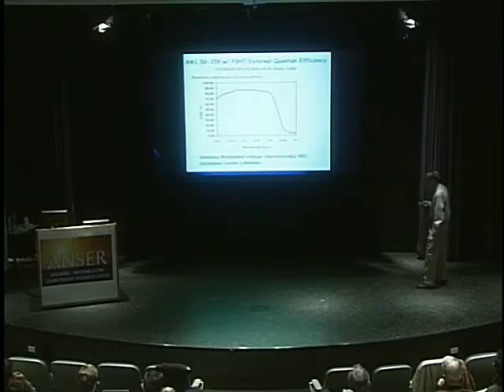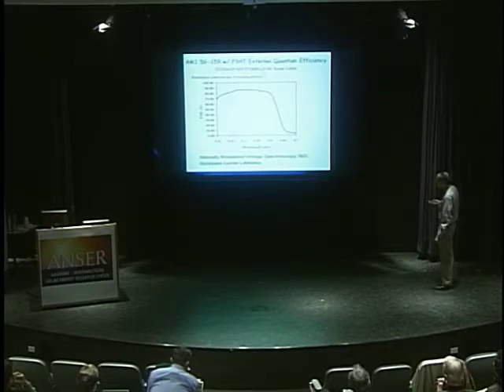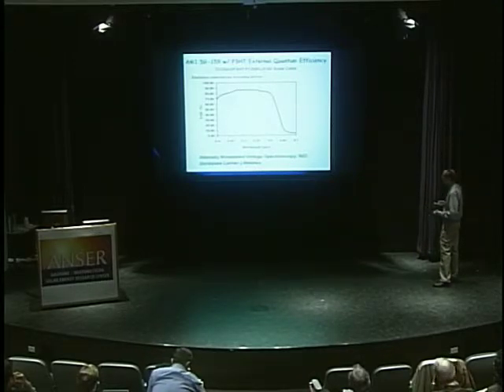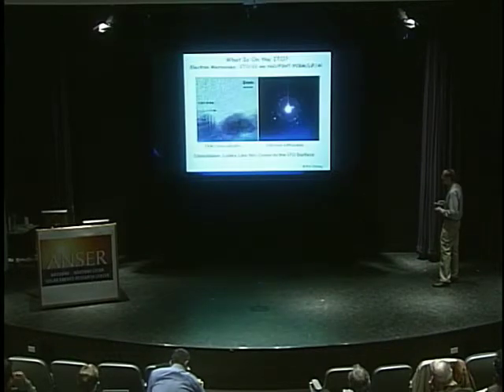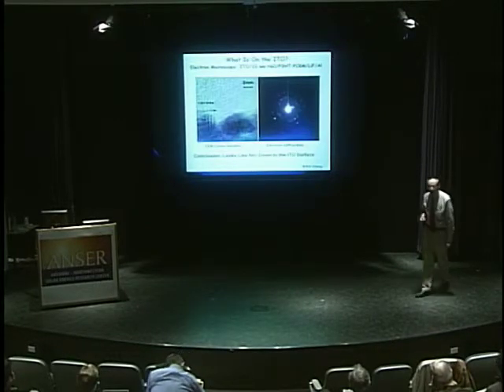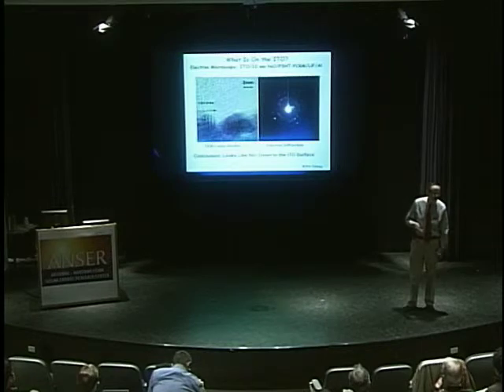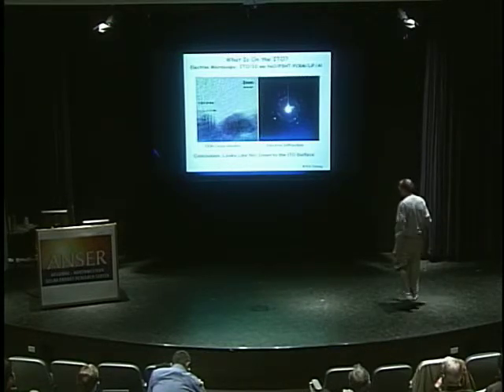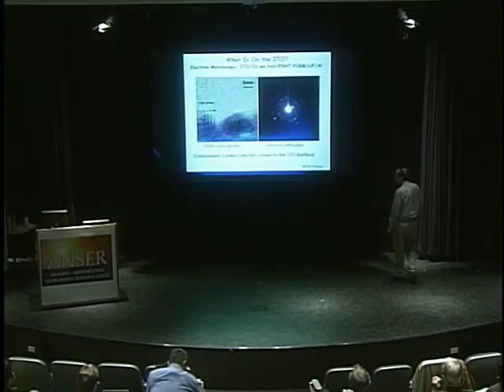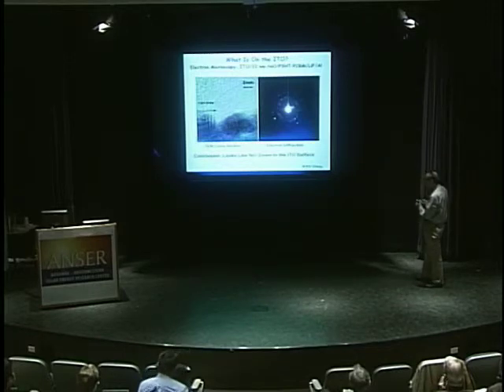The intensity modulated photovoltage spectroscopy says that, again, the carrier lifetimes are increased, work with Joe Hupp, just as we saw in that other case. So then you say, well, how the heck do you know? Is it nickel oxide? Could it be some sort of other nickel phase or indium phase, indium nickelate, nickel indate, whatever? And so this is work with Bob Chang.